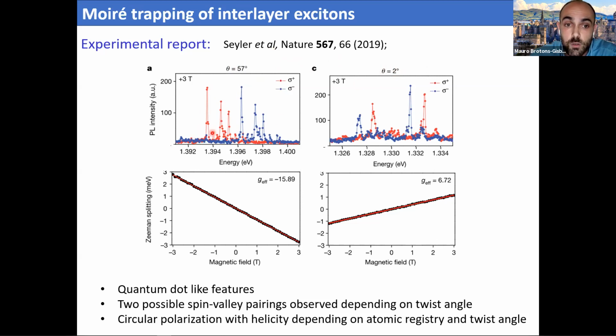And they observed narrow emission lines with circularly polarized emission and with very different g-factors depending on the stacking angle. However, they didn't demonstrate that these trapped excitons are single photon emitters. So we wanted to prove this experimentally.